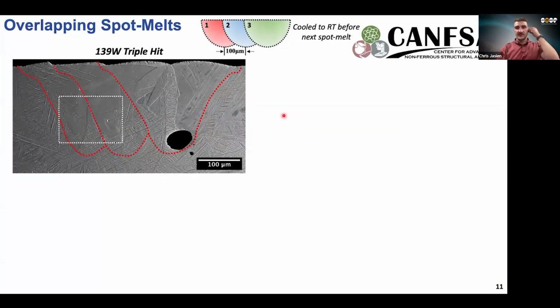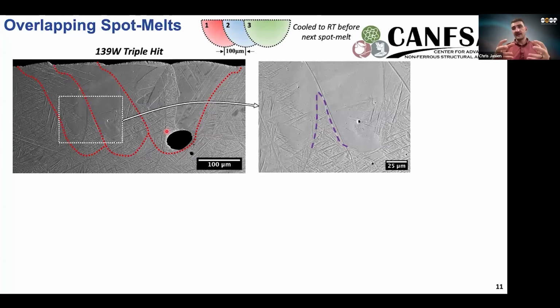Okay, so to further complicate things and understand a little more, we added one more spot melt to the scenario just to see if we're going to see the same things. So we look at the same region of interest, that boundary between the first and second melt pool that we looked at before, and we investigate that further, and we do see a reduction from the bottom of the melt pool to the top as we saw before. However, now it's no longer a gradual decrease. It's actually an abrupt suppression.